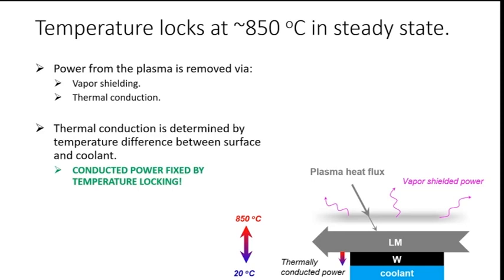And this is actually great because you can easily destroy your sample if you put too much power to the coolant. So you can imagine maybe water will heat up, especially where the plasma hits. And if it starts to boil, if you put too much heat, at some point you have boiling to such an extent that you have zero cooling anymore and your component will just fail. So this is actually a great way to try and avoid that mode of failure. And all the rest of the power has to be vapor shielded. Yeah, that is how you can determine roughly how much power you vapor shield.